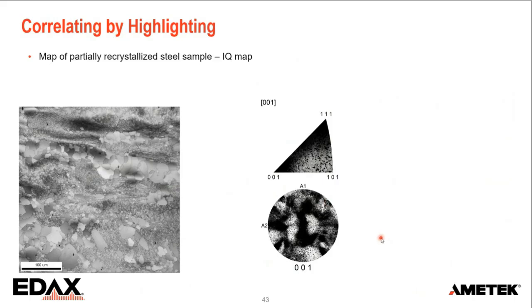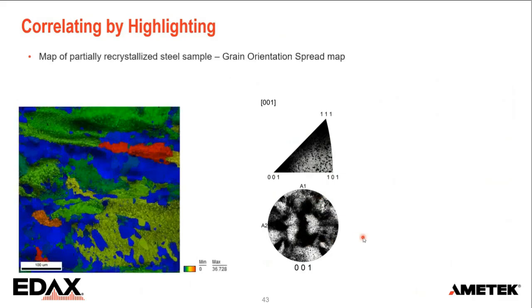Now, how can we visualize that? Because now we really can't see what's happening in those dark parts of the pole figure. So in this case, I just make a grain orientation spread map on top of my IQ. So we can see where the recrystallized grains are in blue. And then I can